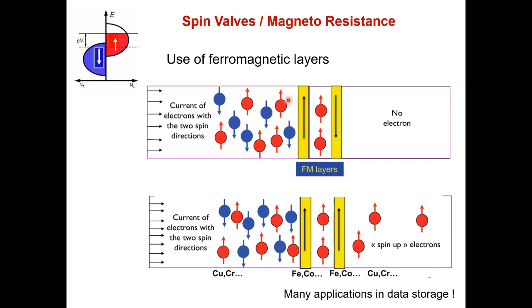So here, before, I have the spin up and the spin down, but only the spin up can cross this ferromagnetic layer. Basically because at the Fermi energy, I have a majority of spin up. Now, if you change the magnetization of the ferromagnet, you will reverse the blue and the red region. You will have a majority of spin down at the Fermi level.